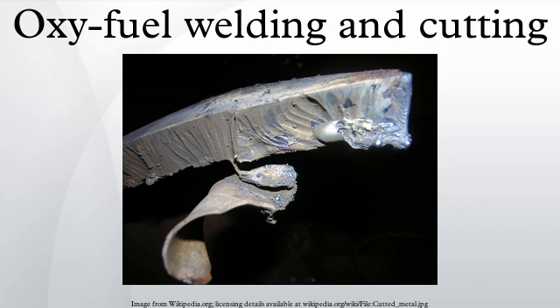Safety. Oxyacetylene welding and cutting is not difficult, but there are a good number of subtle safety points that should be learned, such as, more than 1/7 the capacity of the cylinder should not be used per hour. This causes the acetone inside the acetylene cylinder to come out of the cylinder and contaminate the hose and possibly the torch. Acetylene is dangerous above 1 atmosphere's pressure. It is unstable and explosively decomposes. Proper ventilation when welding will help to avoid large chemical exposure.